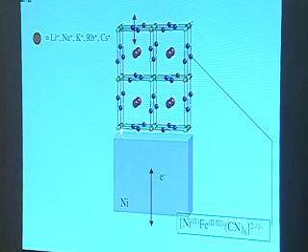Okay, so we need a thick enough layer here that we stop the nickel ion generation. And 1 unit cell, 10 angstroms, won't do that. But 100 angstroms, as long as I don't push the potential too positive, will do that. On the other hand, if I go up to 1,000 angstroms, I can really go to quite positive potentials without any corrosion of the surface. So 100 angstroms to 1,000 angstroms, that is 10 atomic unit cells up to 100 unit cells. That is what we're playing with here.